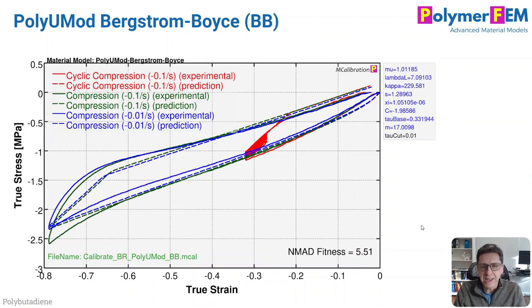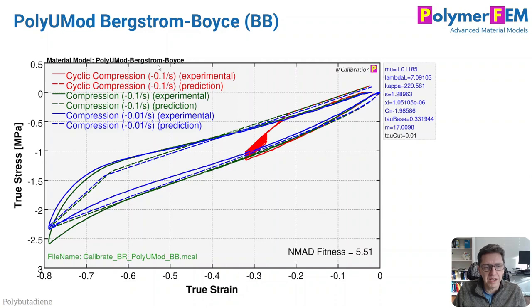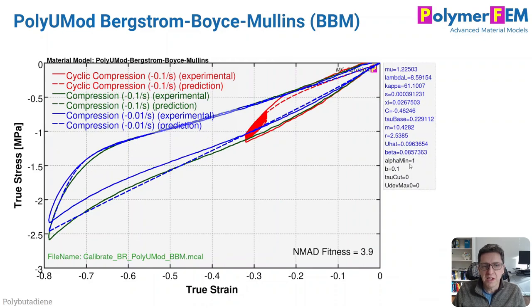The next one is a model I developed: the Bergstrom-Boyce model for rubbers. It actually works surprisingly poorly here too. The reason is that the Bergstrom-Boyce model does not include Mullins damage, so the unloading slope will be the same as the initial slope — which is not what the material does. The error of 5.5% may not sound high, but it really isn't a great fit. If we turn on Mullins damage — Bergstrom-Boyce with Mullins — the error goes down to 3.9% and it looks significantly better.